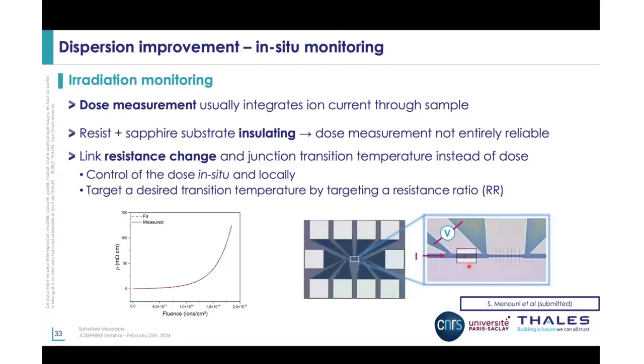And just next to it, we have this micrometric size window where we can actually measure the resistance during the irradiation. So instead of relying on the dose applied by the machine, which again can be not entirely reliable due to the insulating nature of our sample, we rely on the change of resistance that you can see here. Whenever the fluence of the dose increases, the resistance of this window increases. And then we can actually target a certain change of resistance from the initial value to the final value, instead of actually aiming for a dose which again can be different from sample to sample.